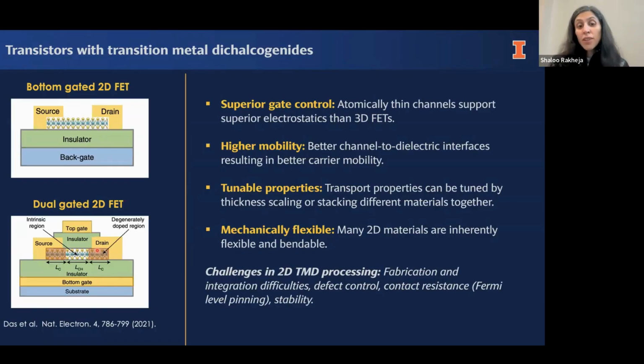And then the one that I'm going to focus on is the mobility. Because these are atomically thin, you're not really getting that interface scattering. So they have really great tunable properties. Why? Because we can stack all these different materials together, which creates a very rich band structure for you to utilize. And finally, and very importantly, these materials are mechanically flexible. So you can strain the materials. I think theoretically, it's been predicted that you can strain them up to 30% without breaking the material, because these materials can deform out of the plane to relax and release the stress that they're feeling. Whereas if you want to strain a 3D material like silicon, the bonds are very rigid. So if you start to strain it, once it reaches a critical strain, which is very small, you will break the material.